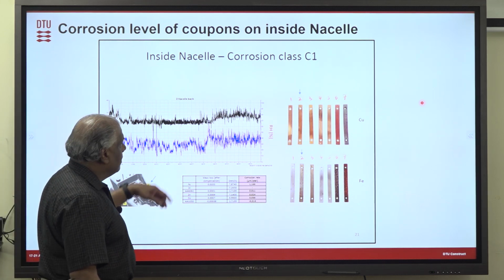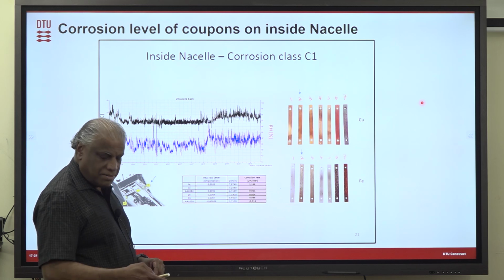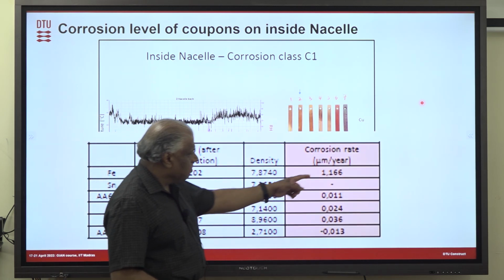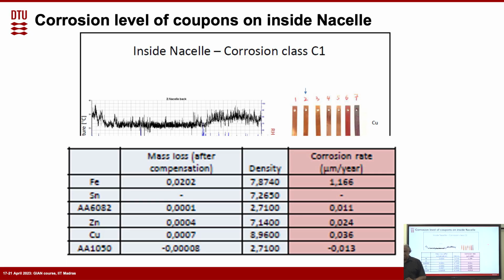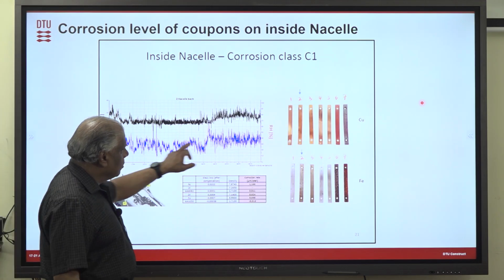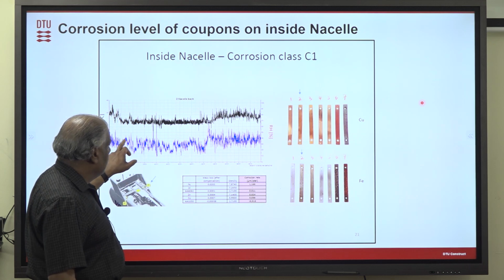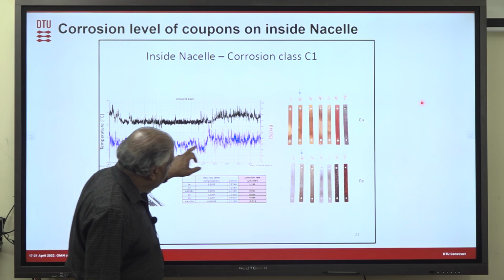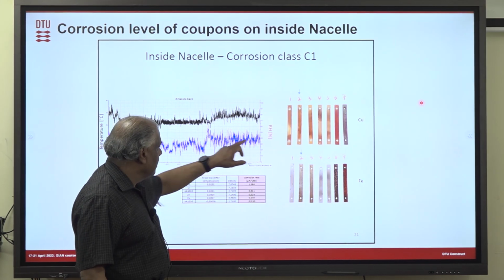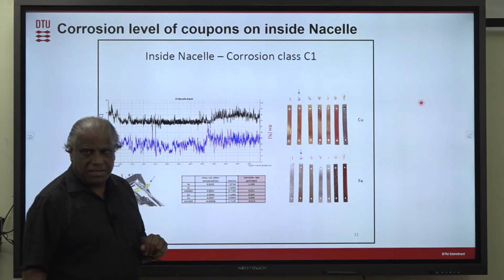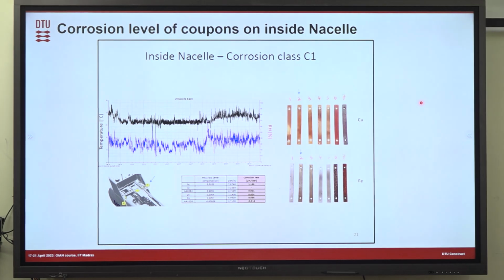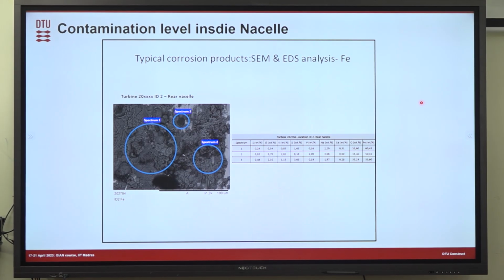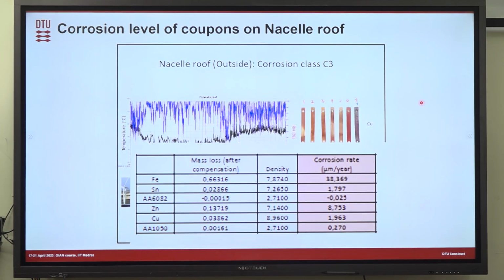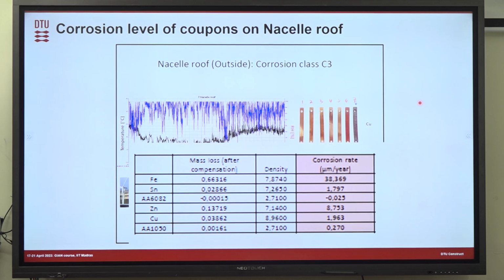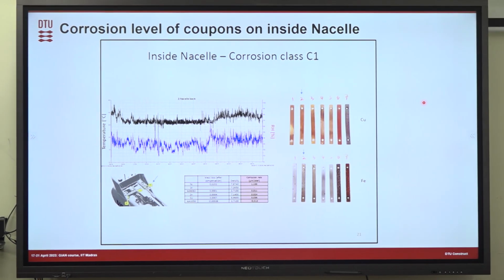whatever is put there, and we determine that the corrosion class is C1, and you can see here that the corrosion rate is much lower compared to that of outside. Inside the nacelle, the humidity level is much lower most of the time. Here you can see that the humidity level is probably only around 60% or 50%, except at some times it has increased, but otherwise the humidity level is lower, and that also gives a lower corrosion rate. So there you can compare that it is corrosion class C3 outside, and the corrosion class is C1 inside the nacelle on the same turbine, for example.